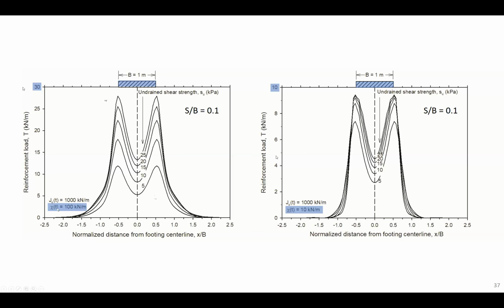You can see this scale is topping out at 30 kilonewtons per meter, and this one's topping out at 10 kilonewtons per meter. The trends are pretty well the same in both cases. You can also see that the loads in the reinforcement, regardless of the actual set of stiffness parameters, is actually higher at the edges of the reinforcement than at the middle. And of course, this difference will depend on the width of the footing, and it will also be influenced by the thickness of the granular layer and also by the strength of the clay foundation, obviously.